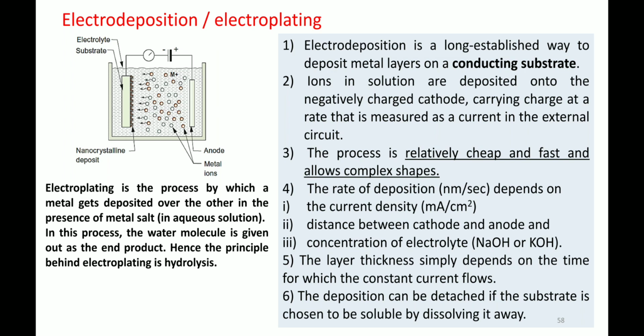So the deposition will be strong enough if your substrate is conducting and highly stable in alkaline electrolyte solution. But if your substrate is not that stable and starts to dissolve in the electrolyte, then you will not get a high quality thin film, because it starts to peel off as the deposition is going on. So that is the necessary condition where you have to choose a conducting substrate which is highly stable in the liquid electrolyte.